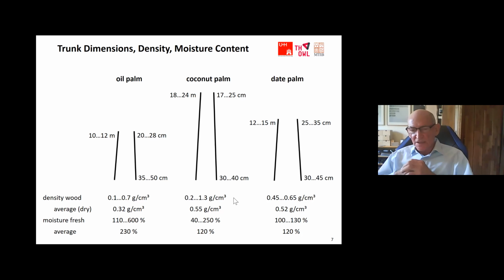So the most important thing is the density of the timber. The average in oil palm is roughly 0.3. In coconut, roughly 0.5 to 0.6, and in date palm, 0.5. And from this, the moisture content in the oil palm is very high because the density is low. And in the coconut palm, the moisture content is lower because the density is high. So the reason for this very different density, you see the variation for the oil palm between 0.1 and 0.7. The same is with coconut palm, but it is not the same as date palm.